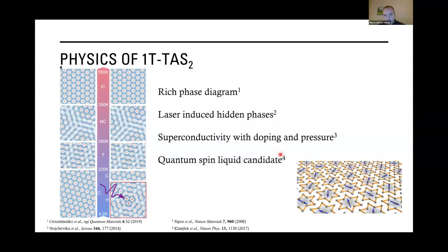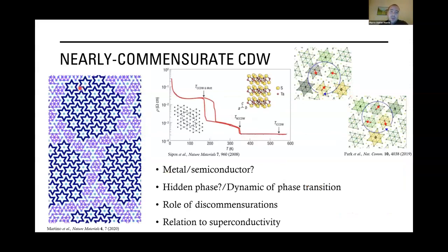But in our work, we are trying to focus, first of all, on this room temperature nearly commensurate charge density wave. And so in this phase, you will have the formation of domains of Star of David clusters. And these domains will be surrounded by a metallic discommensuration, a metallic domain wall. So what is interesting about this material, or what is still not well understood, is what its properties are per se. For example, you have some metal type of behavior. The dynamics of this material, the ultrafast dynamics, show some metallic behavior.